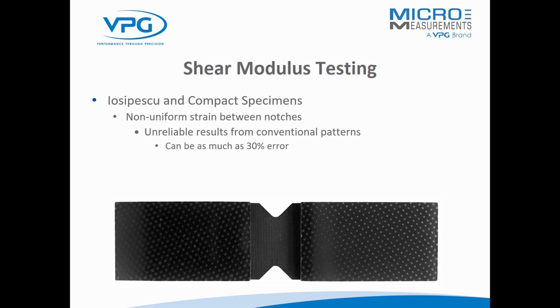This is another example of the shear modulus testing, and this shows the actual coupon, and you can see the shape of it, sort of like a bow tie. You'll see the 2 notches, and the gauges are sized to cover that entire distance between those 2 notches. The reason for that is it helps to make the shear modulus calculations much more repeatable as you start testing materials that have various fiber directions. If you were covering just a small section in between the 2 notches, you'd find more scatter in your data when you calculate the shear modulus as the fiber orientation varies. So to make that more repeatable, we developed strain gauges years ago that help to average out some of that non-uniformity that you see as you have different orientations of fibers.